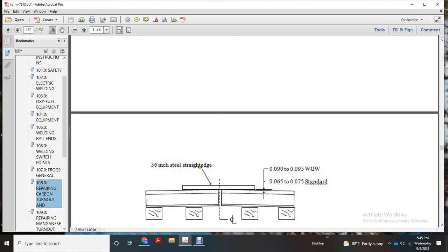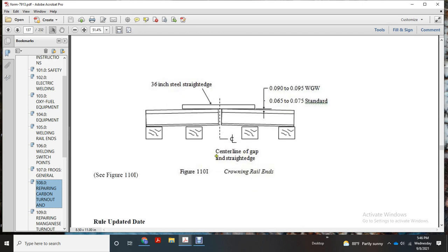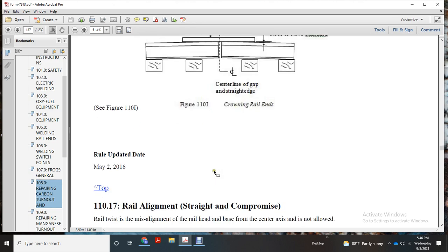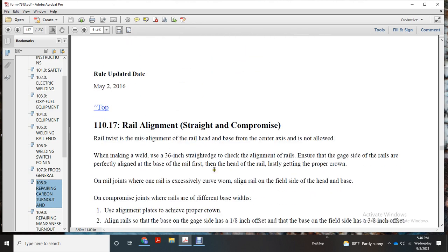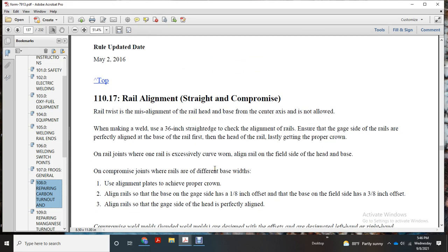Show the 36 inch steel straight edge with a wide gap or standard gap, the center line of the gap in the straight edge, and the crown. Rail alignment, straight and compromise. Rail twist and misalignment of the rail head and base from the center axis is not allowed when making a weld. With a 36 inch straight edge, check the alignment of the rails and line up the gauge with the rail, in a perfect line with the base of the rail first and the head of the rail last, getting the proper crown.